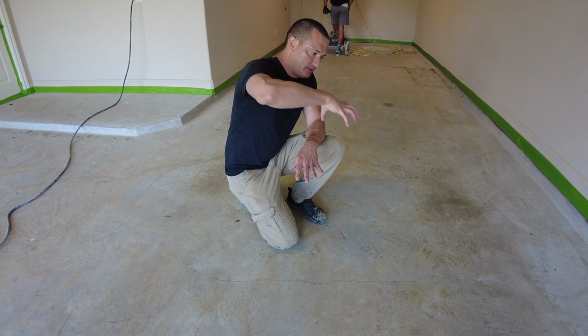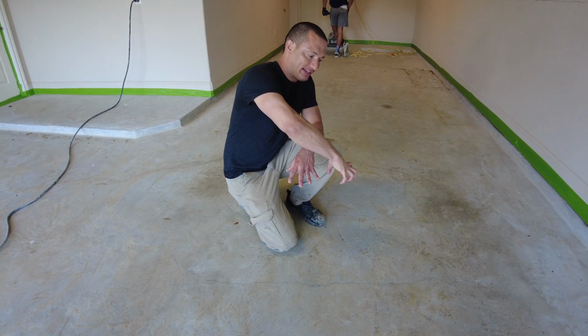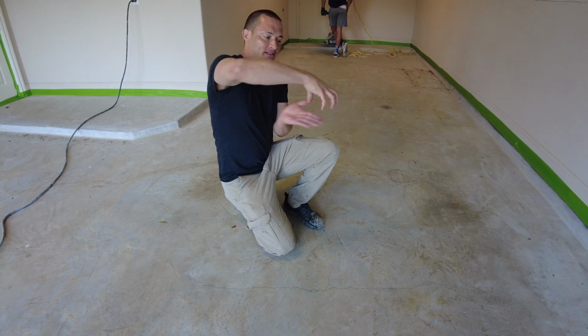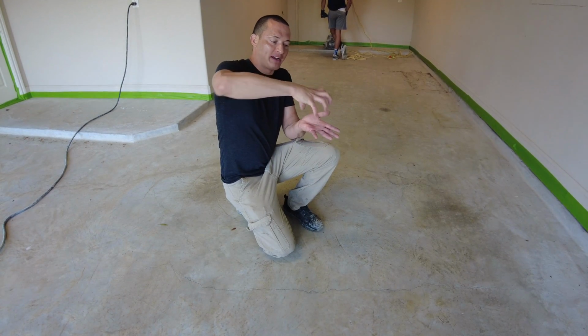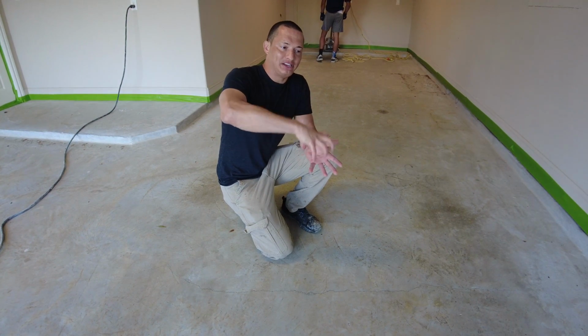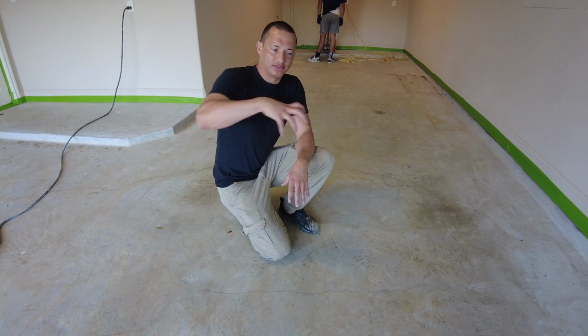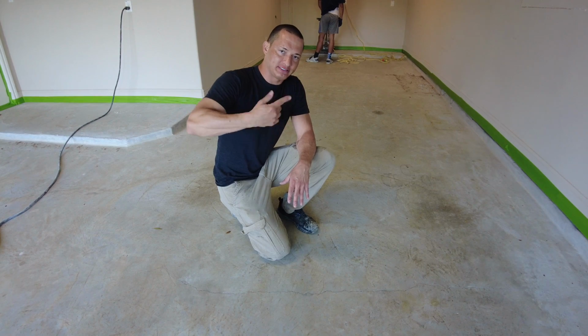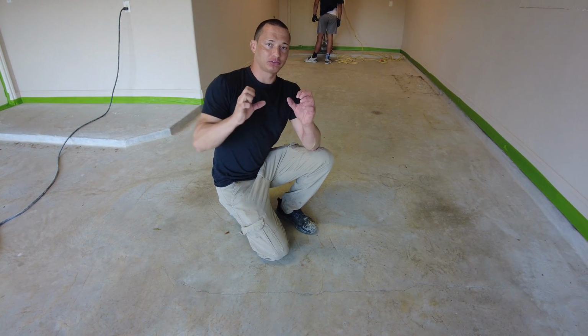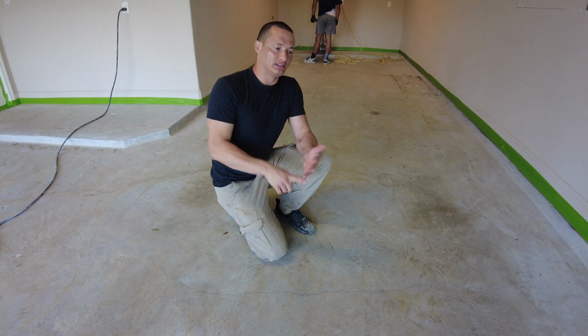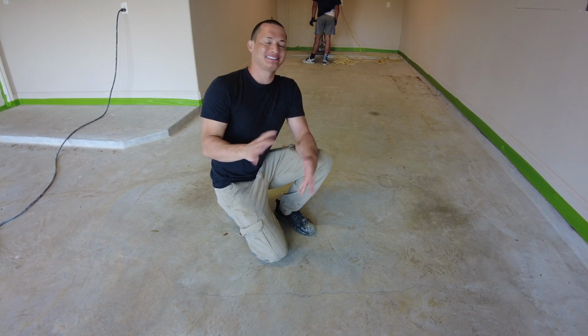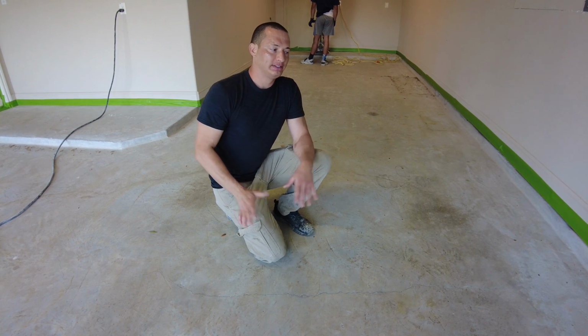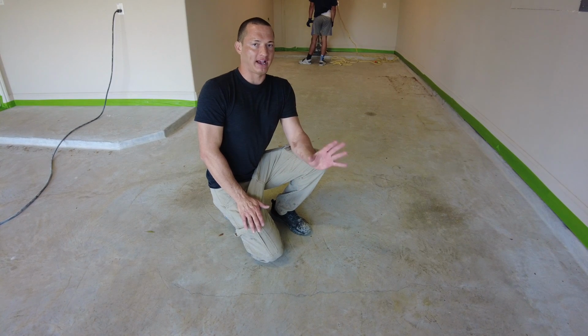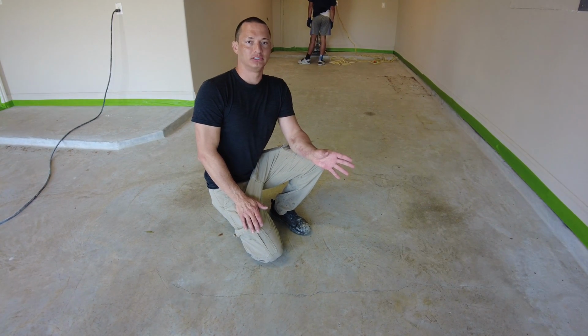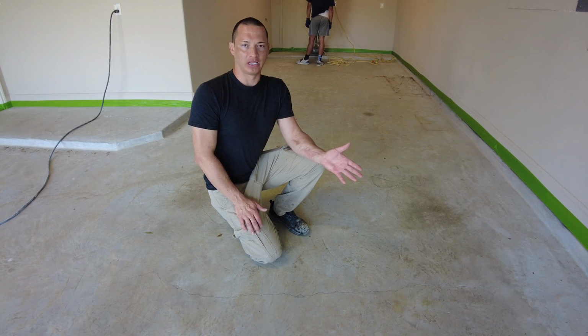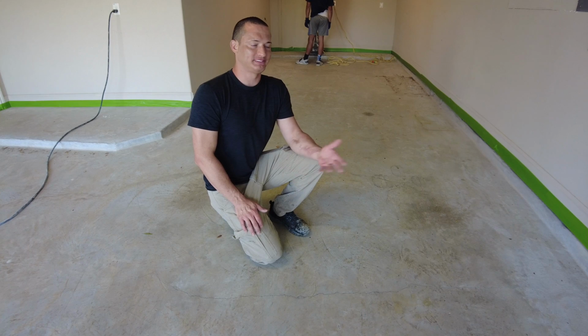When you have the coating in the concrete like it should be anchored, and you pull it, the thin outer layer when it breaks apart, that's called the adhesion strength. There's different ways to measure product strength. There's tensile strength, there's adhesion strength, there's shear strength, there's abrasion resistance, there's tensile hardness, there's flexural strength, there's torsion, there's UV stability, there's acid strengths. There's an infinite number of ways to measure a product strength. So when someone tells you something's stronger, what you need to first ask is, stronger how? If they can't explain that, then they don't know what they're talking about. They're just trying to roll you with some kind of sales pitch.